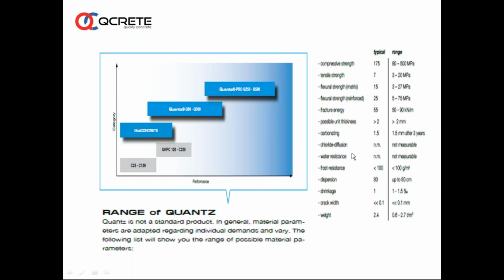Carbonation is less. Chloride ion diffusion not measurable. Water resistance not measurable because it is an extraordinary material, a different material, and the normal available standards cannot give the values for such an advanced material. Frost resistance,